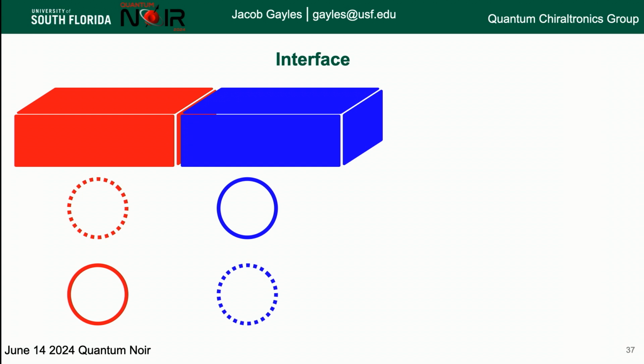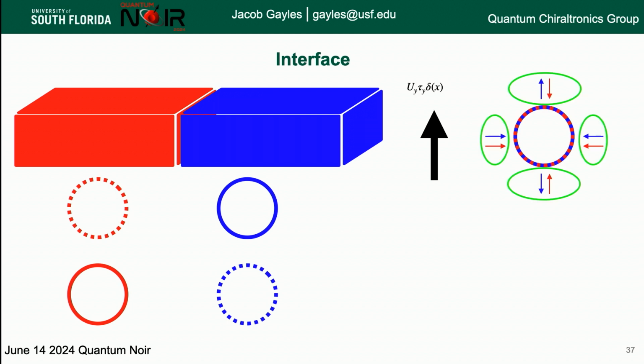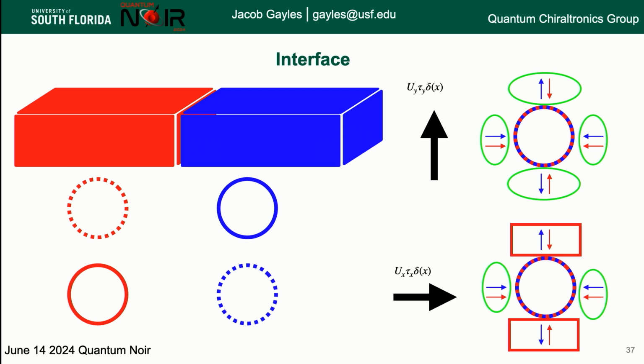And the other aspect of why this is interesting, the last slide of physics, is that you can actually make very nice spin filtering devices. When you have some magnetization texture at the interface, you can allow all the spins, and when you change the direction, you start to block spins that go through. So it's almost like the giant magnetoresistance that I explained earlier, without any ferromagnetic materials.